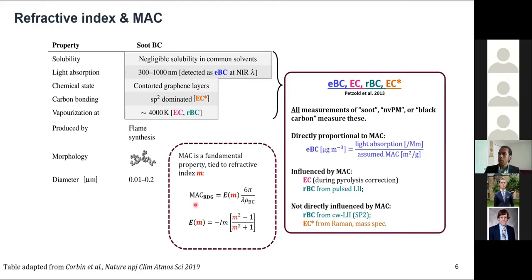So when we talk about MAC, you may prefer to think in terms of refractive index or absorption function E of M, which is a simple function of refractive index. If you do so, you will be assuming a Rayleigh-Debye-Gans model, and this model will come back later in the talk.